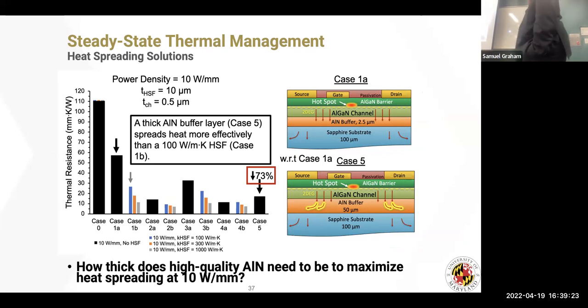Okay, so here's another one. Here's one where we just have the sapphire, low thermal conductivity. This is our base case here. We put no passivation layer on top. And what we do is we have our collaborator just grow a thicker layer. So instead of 2.5 micron aluminum nitride, 50 microns of aluminum nitride here. And you can see the dramatic decrease from here. This one here, we're closer to 60, a 73% decrease in the thermal resistance just by making this layer thicker.